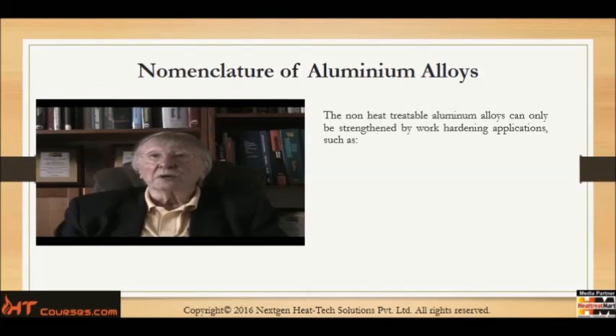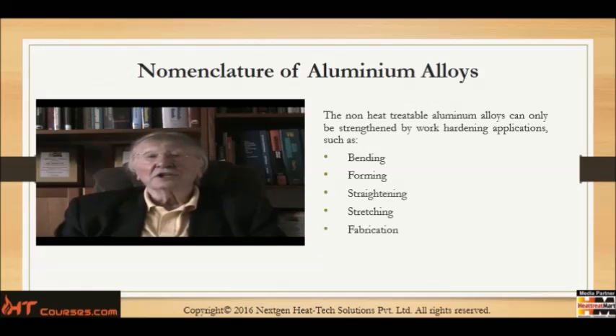The non-heat treatable aluminum alloys can only be strengthened by work hardening, through operations like bending, forming, straightening, stretching, fabrication, drawing, and extrusion. The only thermal treatment that can be given to non-heat treatable aluminum alloys is annealing or stress relieving. There are no other thermal strengthening treatments that can be applied to these alloys.